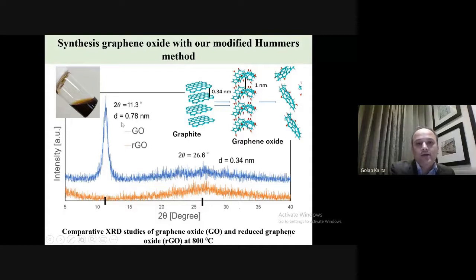Again, when you reduce it, and we reduce by annealing, reduce means you remove most of the oxygen. Then these peaks go down again, and you have just a small graphite-related peak here.